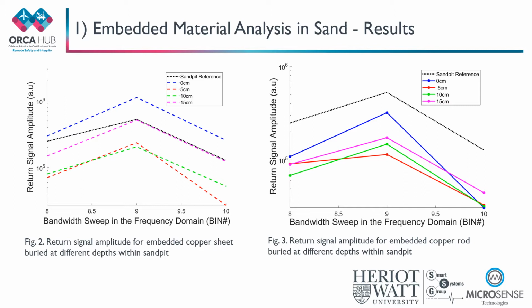These results display that embedded material return signal amplitude decreases incrementally as a function of increasing the burial depth. This is observed for the copper sheet in figure 2 and copper rod in figure 3. This decreasing trend in return signal amplitude is due to more grains of sand being between the radar and copper sheet, therefore scattering and absorbing the signal to the receiver.